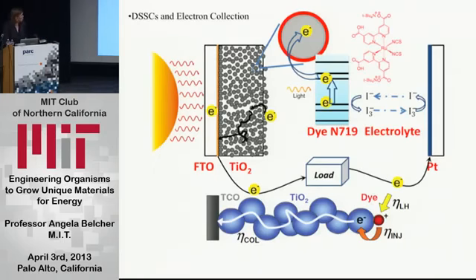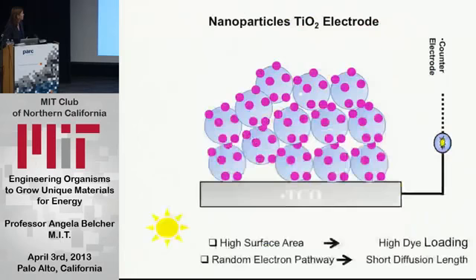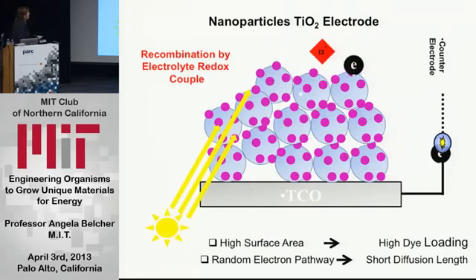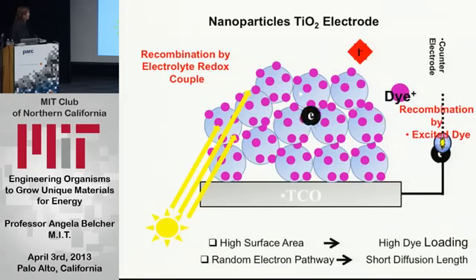And so what my students said was, what can we do to improve this system? So you shine light, you have an electron. The electron is making its way through to the transparent conductor. Things can happen to it. You can have recombination with the electrolyte along the way. You can have recombination with the dye and not make it to the transparent conductor. And so you have a high surface area and high dye loading, but you have a random electron path and you have a short diffusion length.